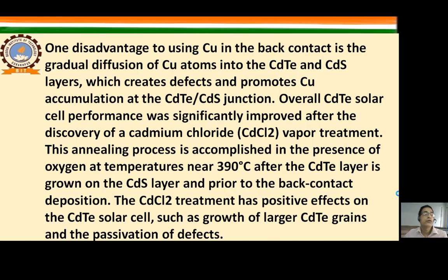One disadvantage to using copper in the back contact is the gradual diffusion of copper atoms into the CdTe and CdS layers, which creates defects and promotes copper accumulation at the CdTe and CdS junction. Overall, CdTe solar cell performance was significantly improved after the discovery of a cadmium chloride CdCl2 vapor treatment.